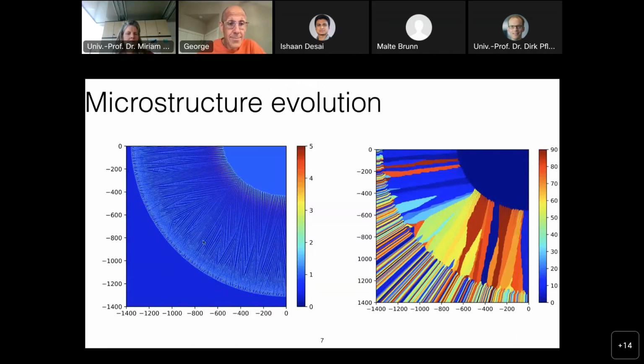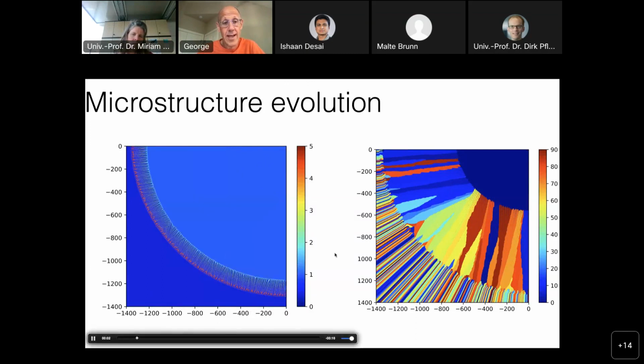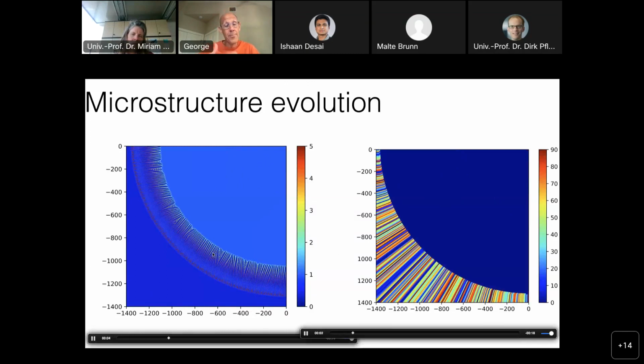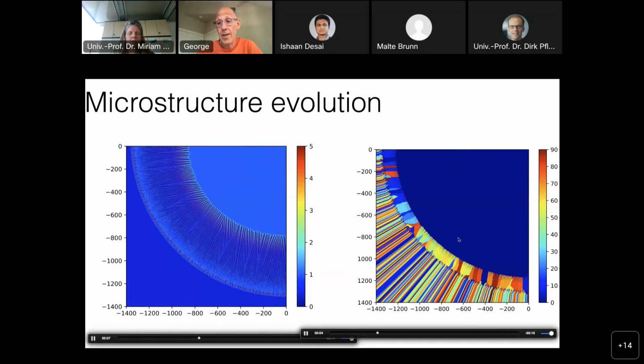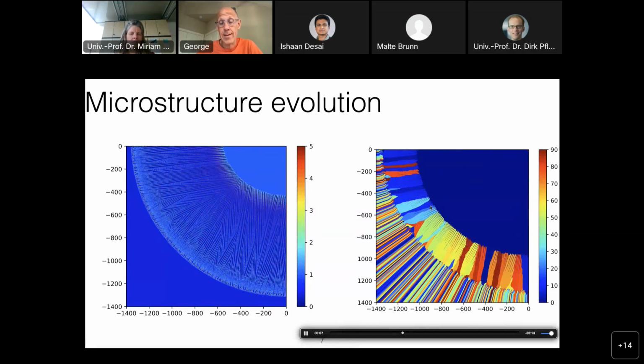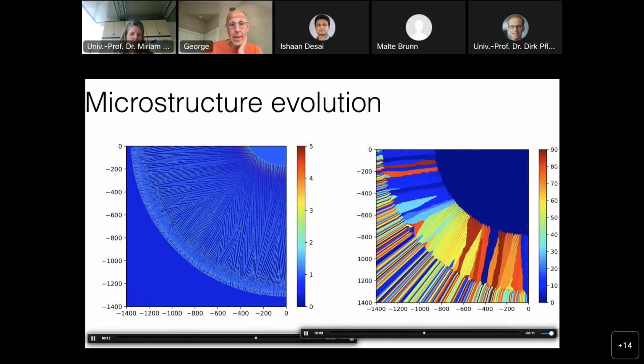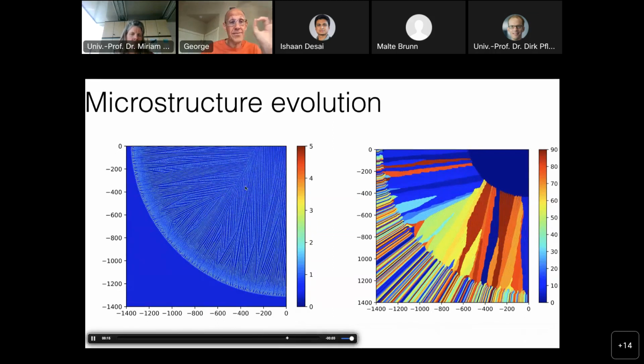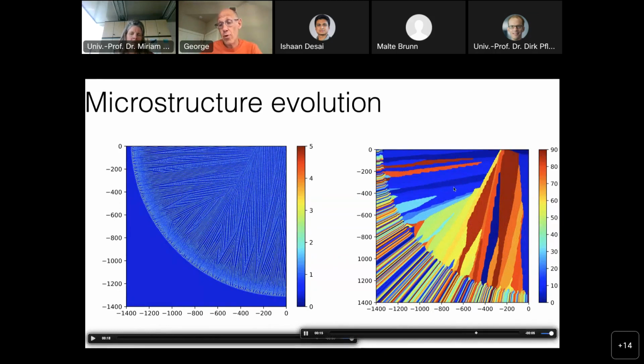Now you can probably see the different orientations here. For example, you can see dendrites growing in this direction, and dendrites growing in this direction, and dendrites growing in this direction. These are essentially different grains, with these directions captured in this figure, and that's another simulation in which we can map this dendrite formation to the grains. So there are two problems here: capturing the alloy variations in the specific dendrite microstructure, and the second problem, which is perhaps a little bit easier, capturing the grain distribution.